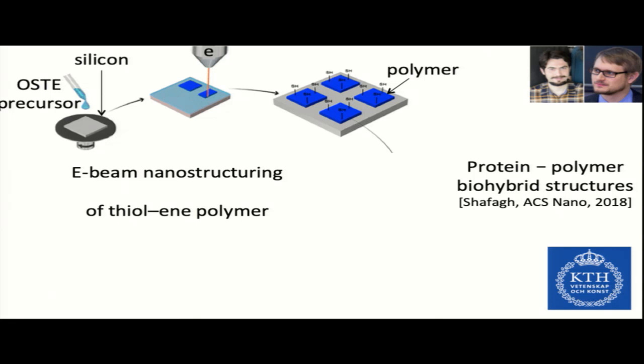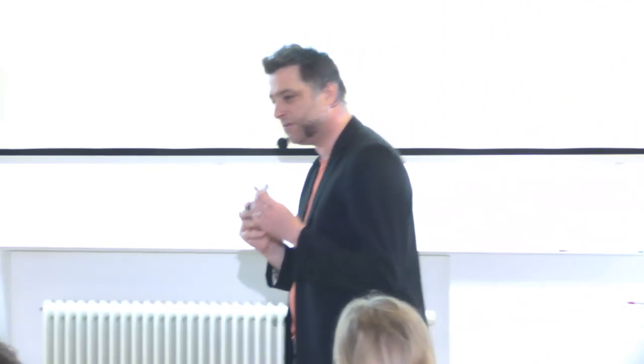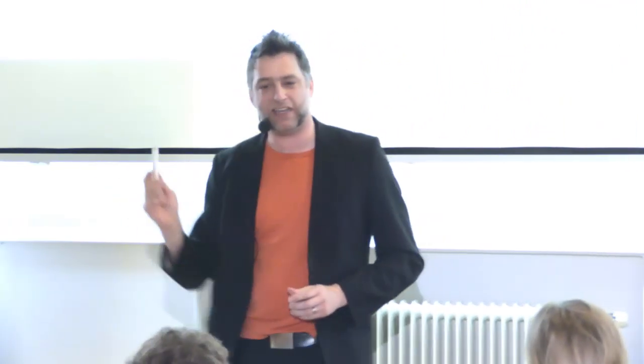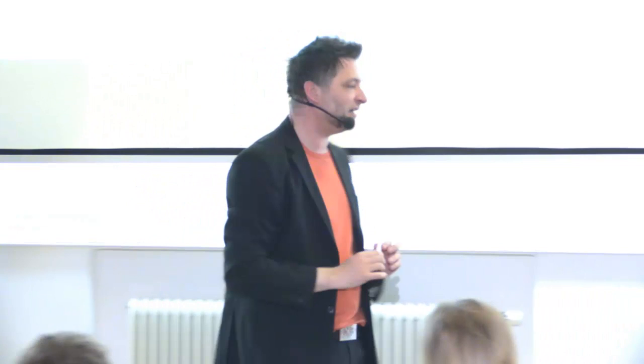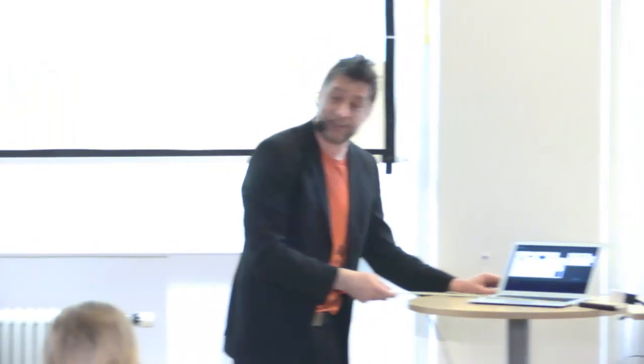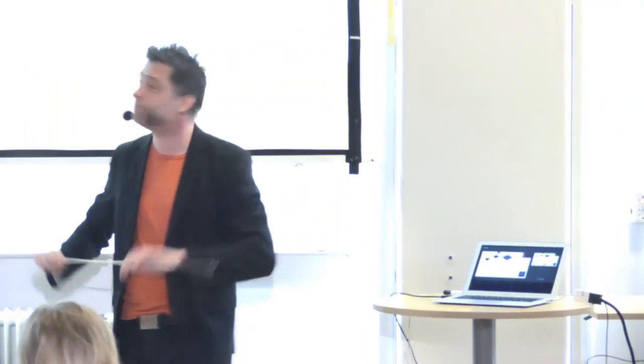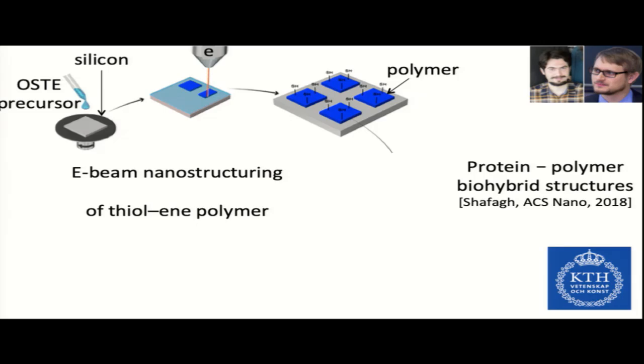And the special thing here is that our polymer is not a normal polymer. Like, for example, this pen, this plastic. Plastic in everyday life is an inert material. Yeah? It doesn't stick, it doesn't react with anything. But the plastics that we make are specifically made to be reactive. So although it's a hard plastic, it has a surface that is reactive with thiol molecules, so sulfur-hydrogen bonds. And these bonds will readily interact with reactive species around them.